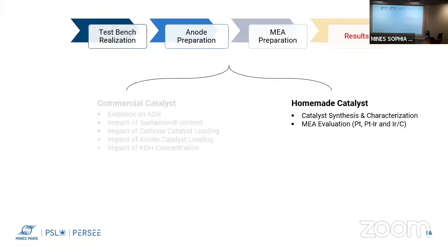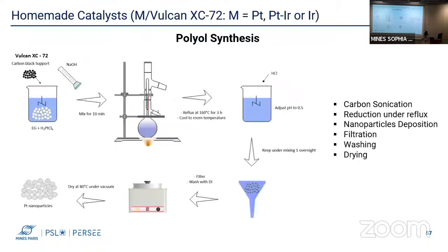Now, for the commercial catalysts, we prepare single metallic platinum and iridium supported on carbon, as well as bimetallic platinum iridium on carbon. We use the polyol synthesis, which consists in reducing the metal salts into metal nanoparticles, using a strong reducing agent, ethylene glycol, and a temperature of 160 degrees C. Carbon black Vulcan XC72 was used, which is similar to that in a commercial catalyst. Hydrochloric acid was used in order to enhance the deposition of the nanoparticles on the carbon support. After that, the mixture was filtered, washed, and dried in order to obtain the supported nanoparticles.